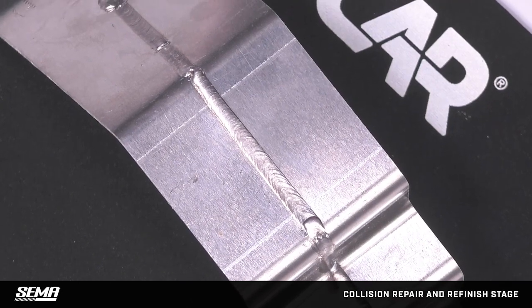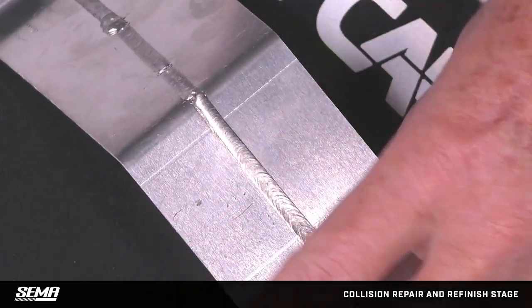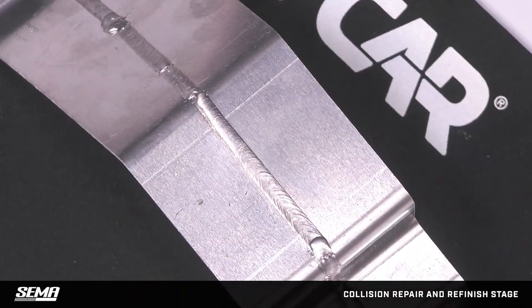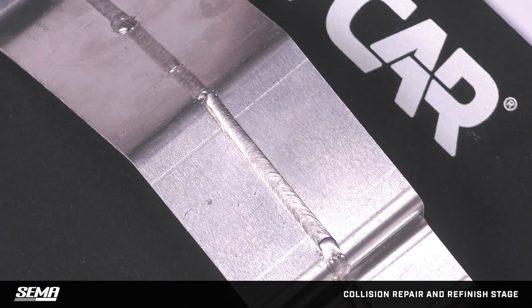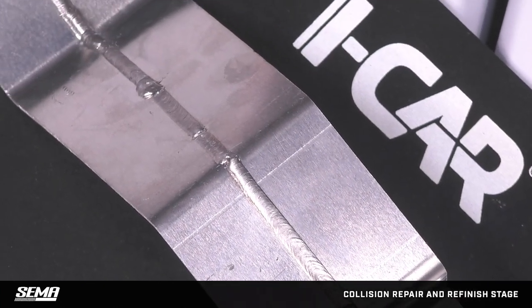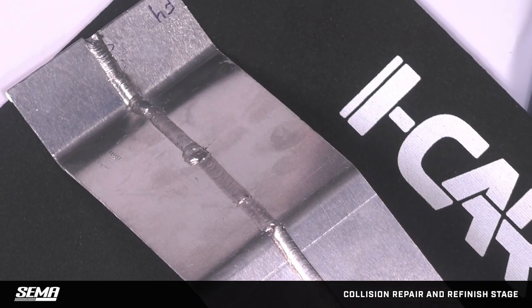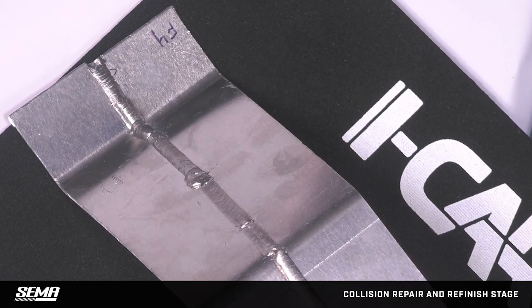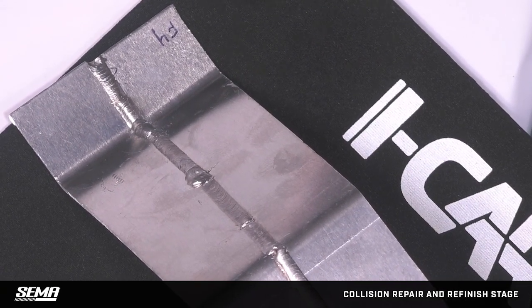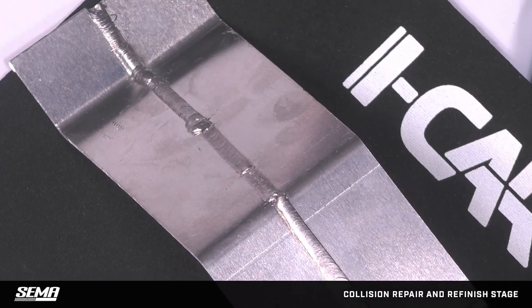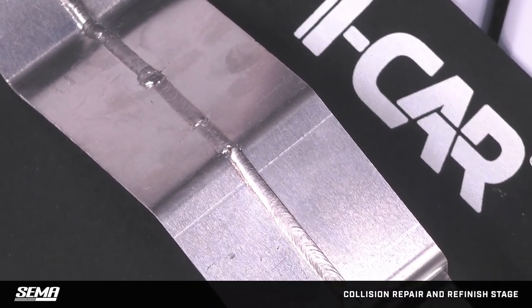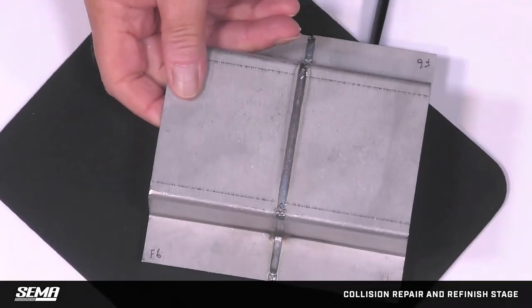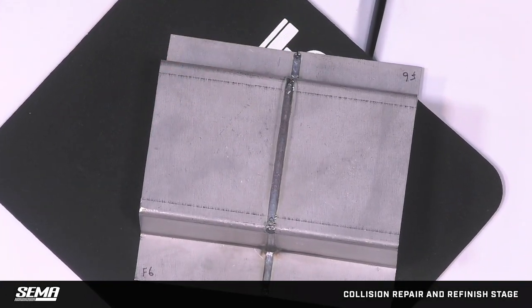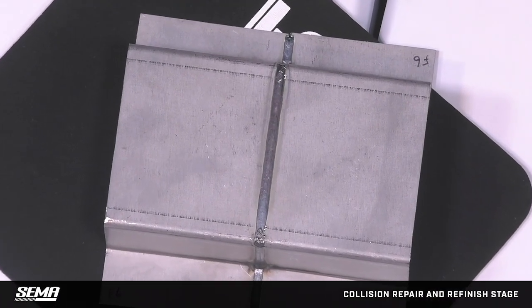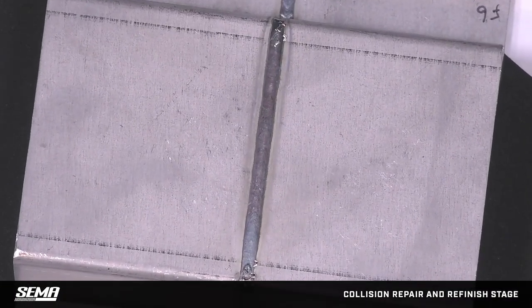Right. And that piece we've got there kind of replicates a rocker section out of a Land Rover, Jaguar, anything that's aluminum intensive. And in that hat channel, as we call it, you've got a vertical, a horizontal, and an overhead, and we were able to run that with one pass with a laser weld all the way around very quickly. I mean, that weld took, what do you think, Jeff, 4 or 5 seconds? It's fast. I will say this: none of these welds were done by me because I'm not that good.